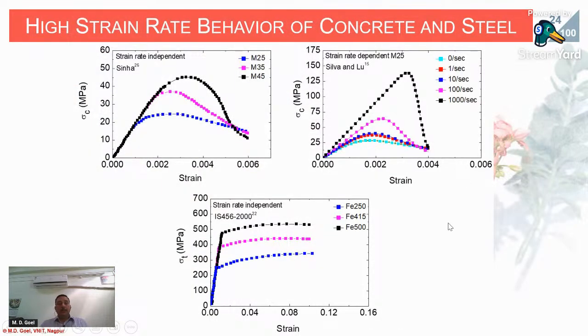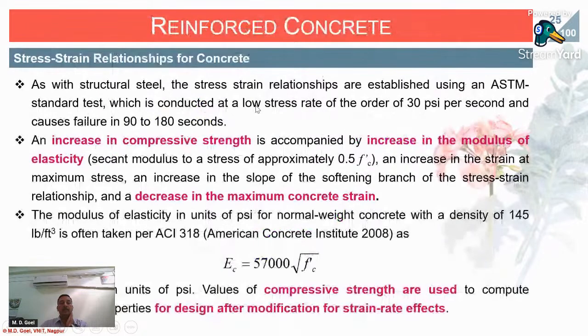This typical slide shows you the effect of strain rate which was tested for M25 concrete. M25 concrete was tested at 0 per second, meaning quasi-static, and we kept on changing the strain rate, and we went up to 1000 per second. You can see this M25 went up to 140 or 150 MPa. So it is giving you a four-fold increase in the strength, and similar behavior will be observed with respect to Fe250, 415, 500, and so on.